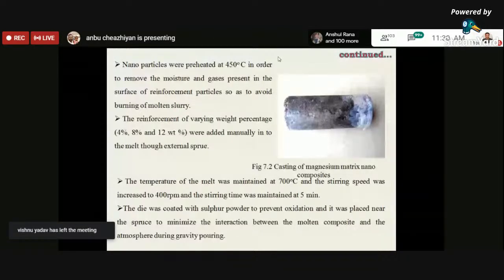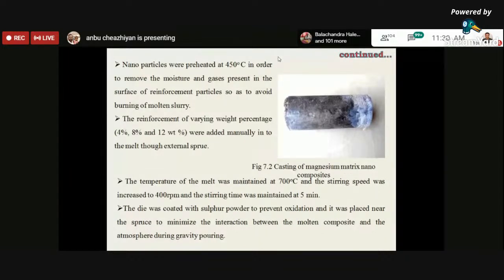After that, various weight percentages of reinforcement particles are added manually into the melt. The stirring temperature was 700 degrees centigrade, the stirring speed was increased to 400 rpm, and it was maintained for 5 minutes. Finally, the molten slurry is poured into the die cavity. The die is coated with sulfur to prevent oxidation, and it is placed near the sprue to minimize the interaction between the molten composite and the atmosphere during gravity pouring.